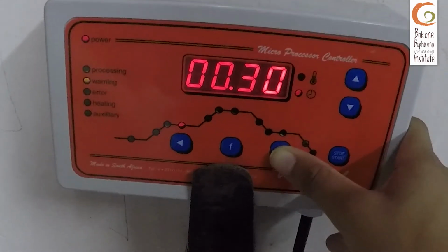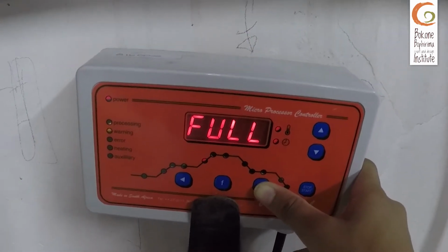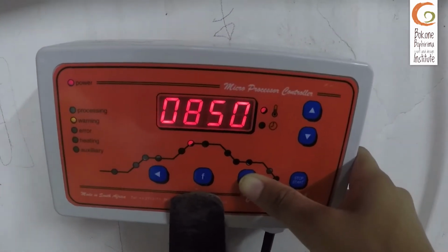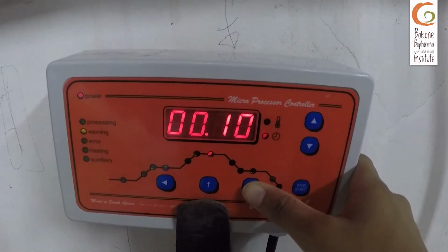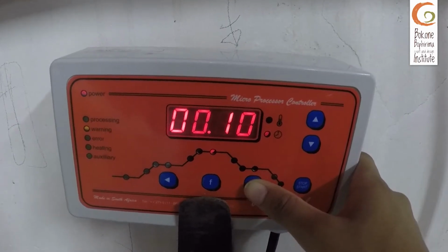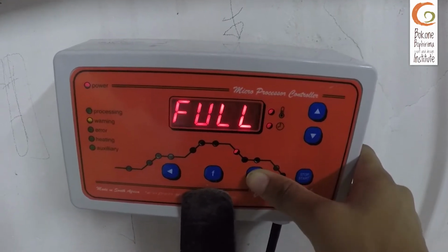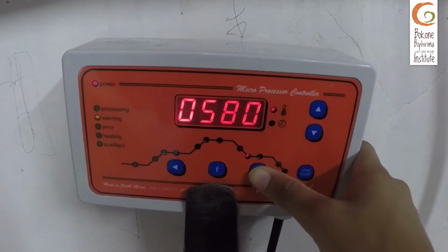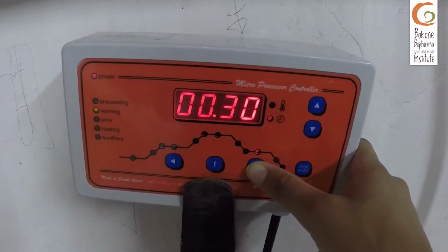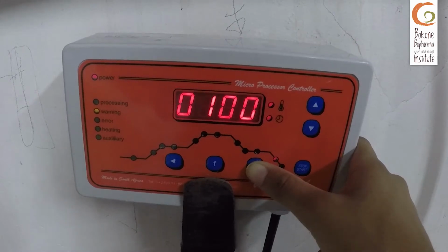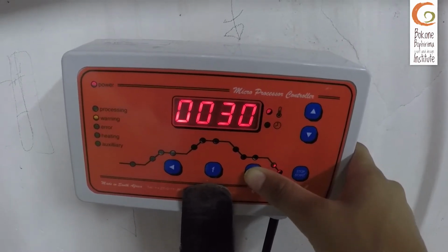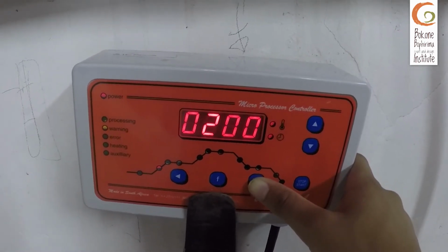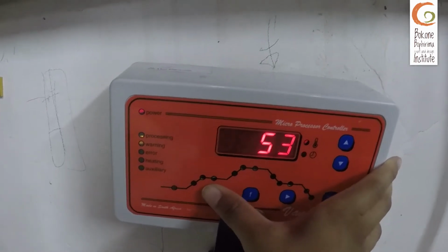And we go up the ramp full up to 850 degrees and hold it for 10 minutes so that the glass can fuse all around. And we go to 580 degrees and we hold it for 13 minutes and pull down to 100 to 30. Once we're satisfied with our program, we press start and we close the kiln at 100 degrees Celsius.